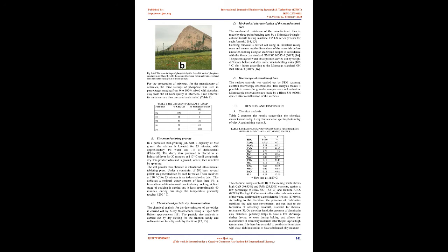The wet powder thus obtained is introduced into a manual tableting press. Under a constraint of 200 bar, several pellets are generated, 10 for each formula. These are dried at 170 degrees Celsius for 25 minutes in an industrial roller dryer. This achieves a residual water content of less than 1%, a favorable condition to avoid cracks during cooking.